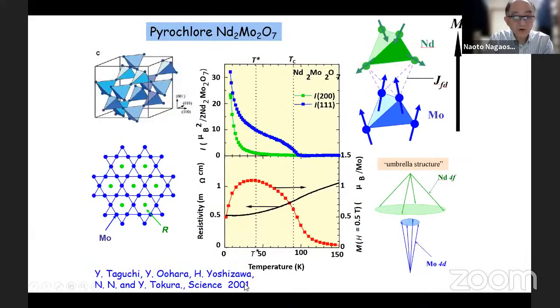And actually, a long time ago, we collaborated with experimental people in Tokyo concerning these pyrochlore materials. So these are pyrochlore materials, and the crystal structure is given here. If you look at this crystal from the 111 direction, then this cross-section contains the so-called Kagome lattice made from molybdenum and neodymium. Because of the very strong single-ion spin anisotropy of the neodymium atoms, the neodymium spins are pointing towards or outwards of this tetrahedron, right?